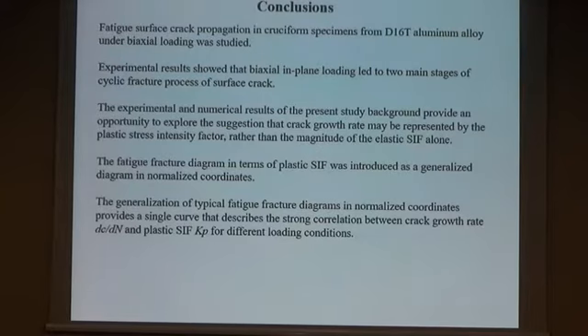So, the conclusions of my talk. Fatigue surface crack propagation in cruciform specimens from D16T aluminum alloy under biaxial loading was studied. Experimental results showed that biaxial loading leads to two main stages of the cyclic fracture process of the surface crack. The experimental and numerical results of the present study provide an opportunity to suggest that crack growth rate may be represented by the plastic stress intensity factor rather than the magnitude of the elastic stress intensity factor alone.